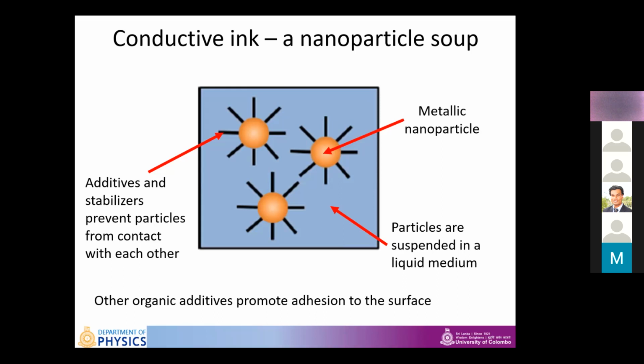Working with paper, the adhesion is not that difficult to achieve, but when you work with substrates such as polymer-based substrates, the adhesion is problematic. We need to enhance the adhesion by adding few additives to the conductive nanoparticle soup. Now, again, once you put this down on a piece of paper or any material, it won't be conductive. We have to make it conductive somehow.